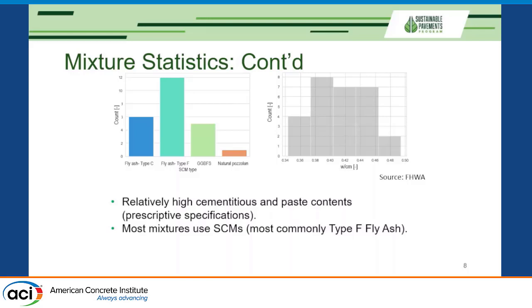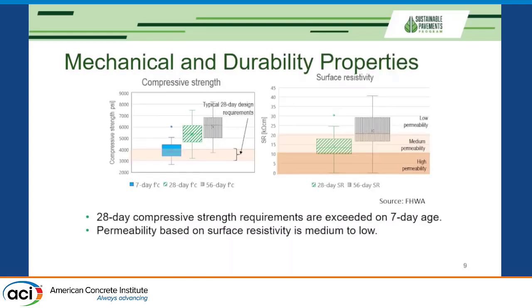And here we wanted to show how it applies also from sustainability and greenhouse gas perspective. So here in this slide, I'm summarizing these box plots of 7-day, 28-day and 56-day compressive strength of these mixes. And you can see here our typical 28-day design requirements in terms of compressive strength. You can see that on average mixes achieve these 28-day design requirements on 7 days already. And at 28-day age, these requirements are exceeded by large margin.